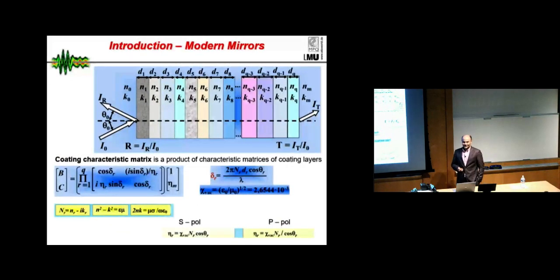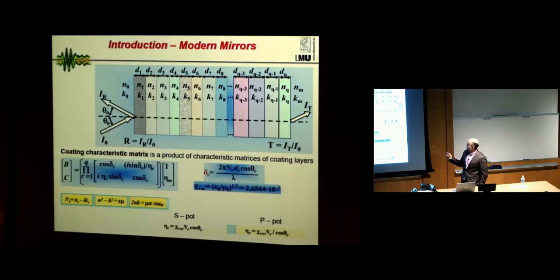We can now get much higher reflectance and control many properties of the coating. And here is just a schematic of how the coating usually looks. We have a substrate, and on top of the substrate, on this side, we put our coating. Basically the coating is called a multilayer coating. It consists of many thin film layers. Each of these layers has a refractive index and an absorption coefficient. All of them have a dispersion as well, if you consider different frequencies. And another important parameter is the thickness.